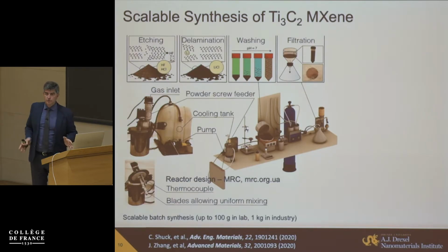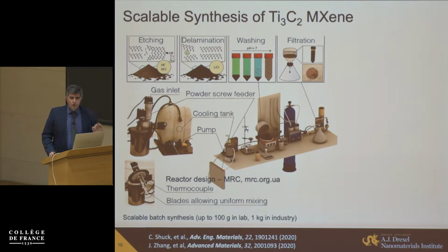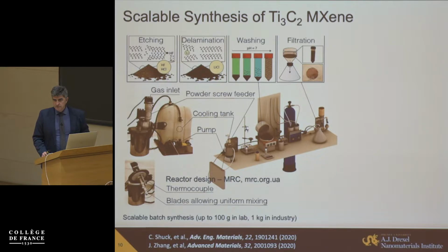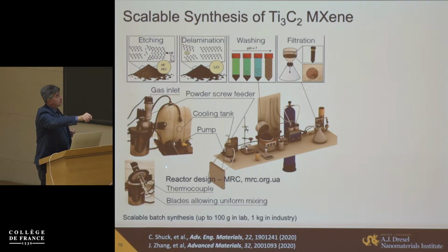What is also very important, you have heard by now about more than 200 two-dimensional materials reported and produced. Just a handful of those can be made in any significant quantities. Here, boron nitride, molybdenum disulfide, graphene oxide, tungsten disulfide, titanium disulfide, and a few others. From day one, we were able to produce MXenes in quantities. Here we have reactors for half a liter, 1 liter, 2 liter, and we can produce up to 100 grams